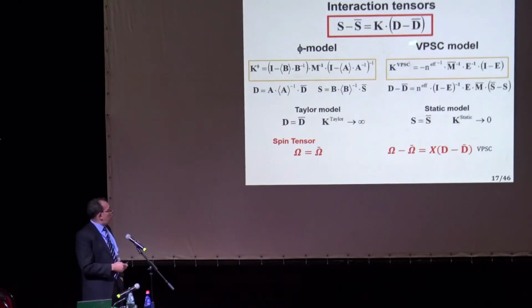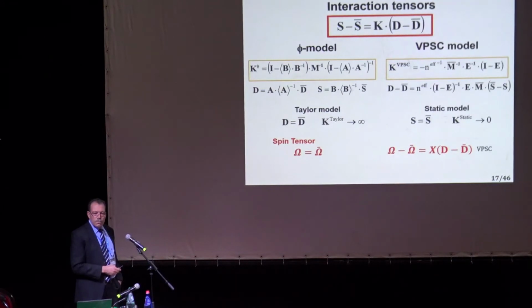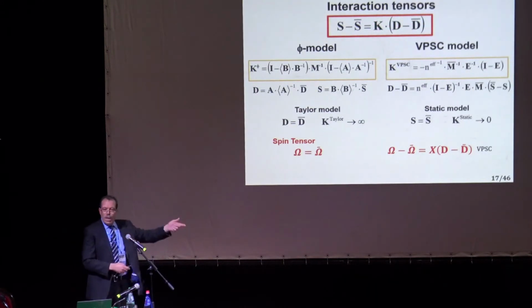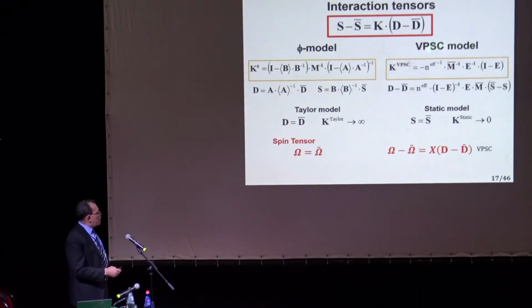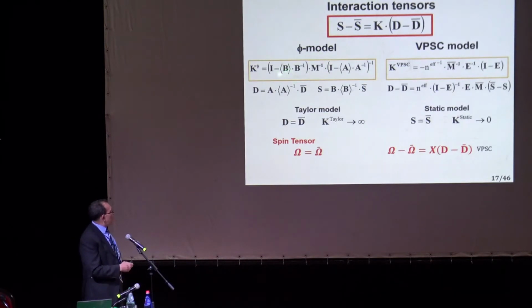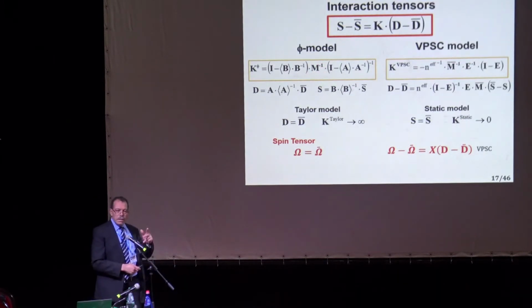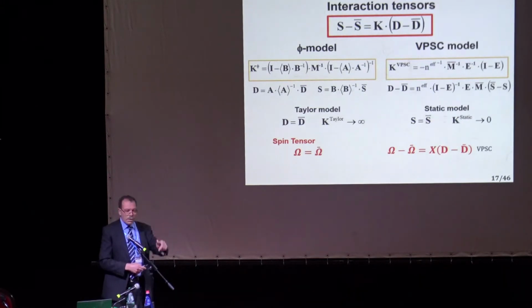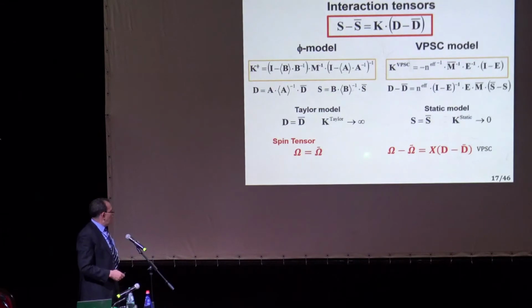So this is how we can write the interaction law for both the self-consistent and the phi model. The difference in stresses is linked to the difference in strain rate through K, which is the inverse of R that I mentioned. Now, in one case, which is the viscoplastic, the K is either N on N effective times this. Or in the phi model, this is what we get. So we have this relationship, and what we should notice is it depends on the compliance. And the compliance has directionality in it. There are cosine directors in it. Whereas here, the viscoplastic depends on the Eshelby tensor, and HLB depends on the effective properties only, not on the local properties. So, just to show, when K goes to infinity, we go to the upper bound, when K goes to 0, we get the lower bound, or what we call Sachs and Taylor.